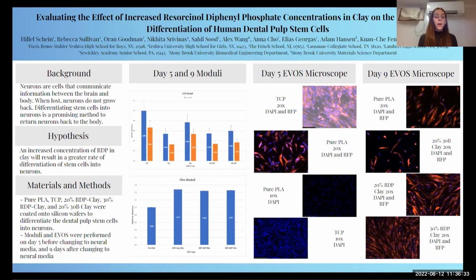We noted that between 20% clay and pure PLA, there was an increase of surface roughness of about 92%. Between 20% RDP and pure PLA, there was an increase of surface roughness by about 89%. And between 30% RDP and pure PLA, there was a surface roughness increase of about 91.64%.